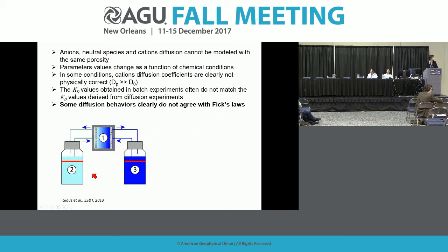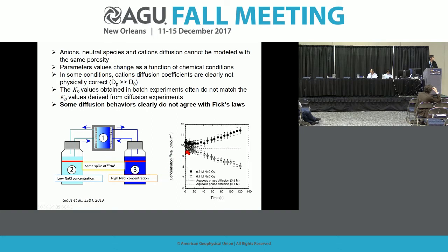So I will show you this example, a very nice experiment from the group of Van Loon et al. in Switzerland. So in fact, they have a diffusion cell with two reservoirs, one reservoir with a low sodium chloride concentration, a reservoir with a high sodium chloride concentration, and at time 0, they spiked the same concentration of a radiotracer, sodium-22. And so what you expect, if there is no gradient, is that Fick's law gives you no flux. But what they could observe is that, in fact, you have an accumulation of this tracer in this reservoir and a depletion of this tracer in this reservoir. So it's a kind of uphill diffusion process.